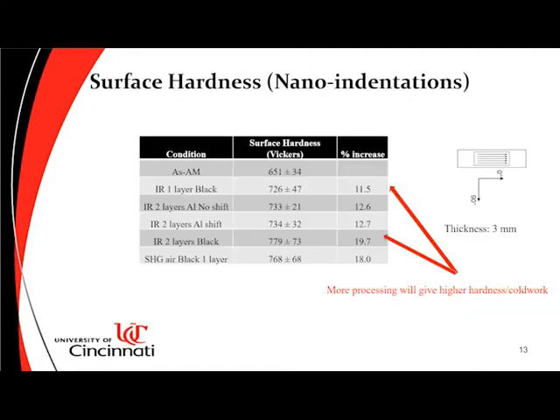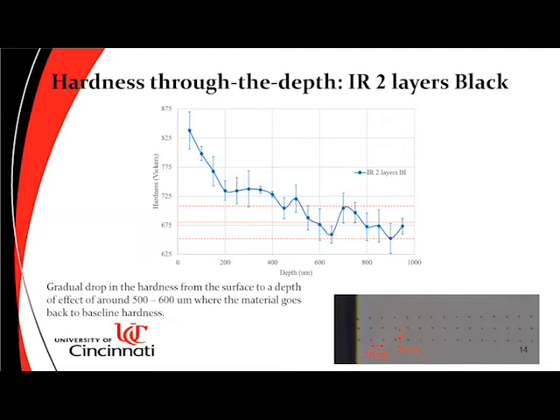So the first thing we looked at after peening is the hardness. LSP is a mechanical treatment that does not produce or induce much cold work into the materials. As seen in here, the surface hardness of the material increases somewhere between 10 and 20%, depending on the peening condition. Looking at the hardness through the depth profile shows maximum increase at the surface, then drops down as we go deeper into the material to reach the baseline hardness at around 500 to 600 microns.